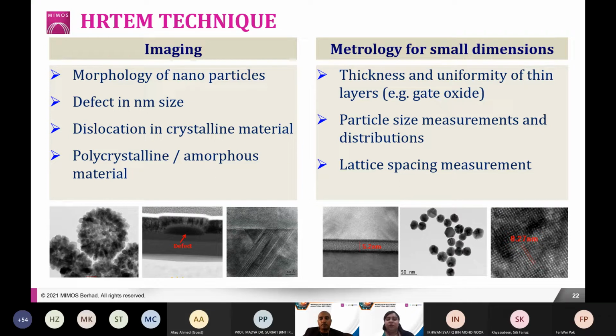And then some customers require measuring the thickness of thin layers. For particle size measurements, we are working together with Nano Verify to verify the nano size particle measurement, whereby companies claim that they have added nanomaterials in their products. This is where we help Nano Verify to confirm the claim, and make sure that the particles measured are in nano size, between 1 to 100 nanometers.